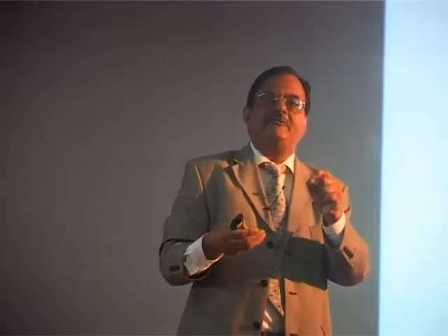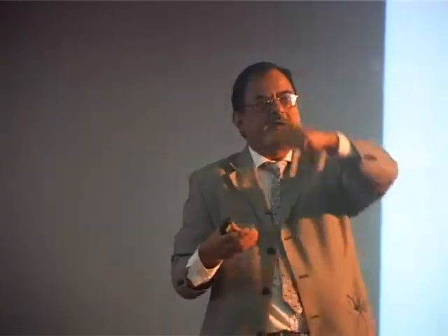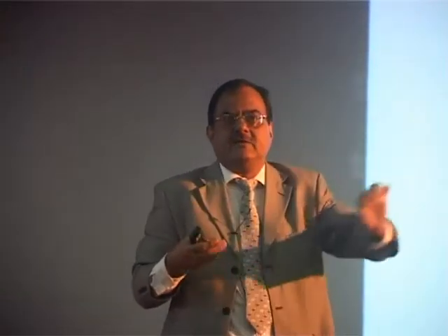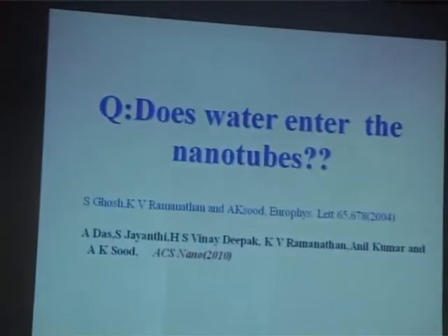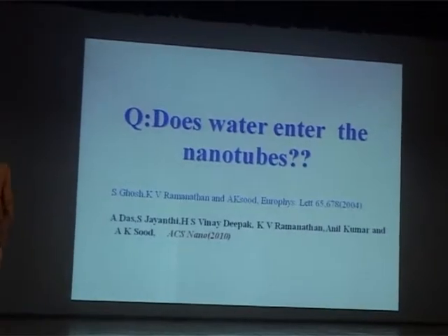People have been doing computer simulations to show that water can enter a nanotube only if it is above 8 angstrom. Below 8 angstrom, water does not enter because there is a hydrophobic distance which water likes to maintain from carbon. So you need 8 angstrom of space. Once you do that, it can enter in the simulations. So we wanted to do an experiment to see what the situation is.